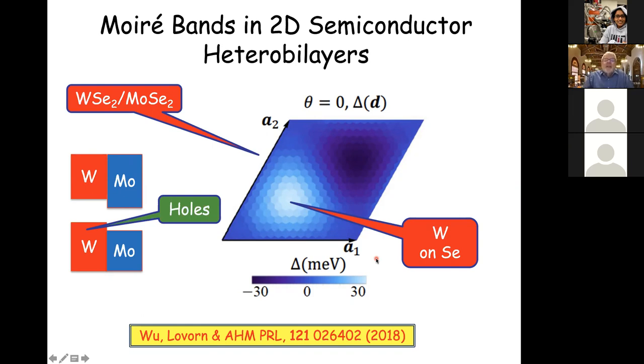And when you have a Moiré pattern, this coordination actually changes slowly on a length of a lattice scale. And the important thing is that because these are two-dimensional semiconductors, the low energy states are very close together in momentum space. And because their momenta are similar, they cannot resolve spatial structure that occurs on a length scale smaller than the reciprocal of the momentum range of interest. And that means that for the electrons at the top of the valence band, for a given momentum, they only see this slowly varying potential, and they're insensitive to the atomic physics.